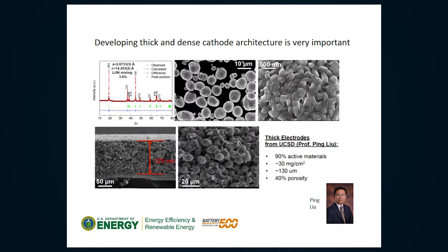Right now, we use, I don't know what Wenjuan is going to talk about, the thickness of the cathode material. For getting to more than 400 watt-hour per kg, the single layer cathode thickness needs to be more than 120 micron in thickness, and with no more than 23 or 5% porosity. That's really difficult to do. That's what we have been able to do, but our porosity is still much higher than needed.